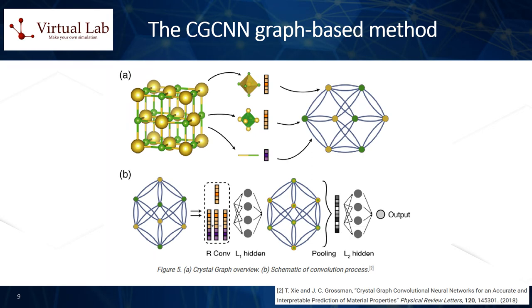The CGCNN is a graph-based neural network capable of predicting the physical properties of the bulk state of materials, formulated originally by Professor Jeffrey Grossman of the Massachusetts Institute of Technology. By introducing the concept of the graph of a crystal structure through flexible encoding of the lattice structure information, this CGCNN method has proven to provide highly accurate learning of the structure-property relations of bulk materials. The CGCNN technique uses about 70,000 datasets provided by the Materials Project database for training the resulting neural network.